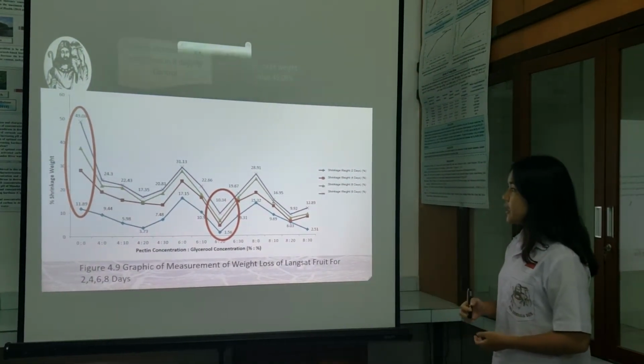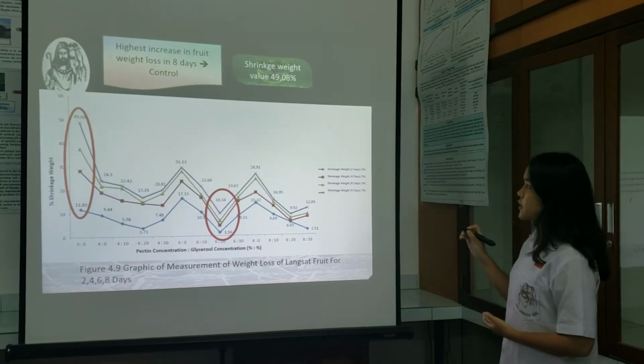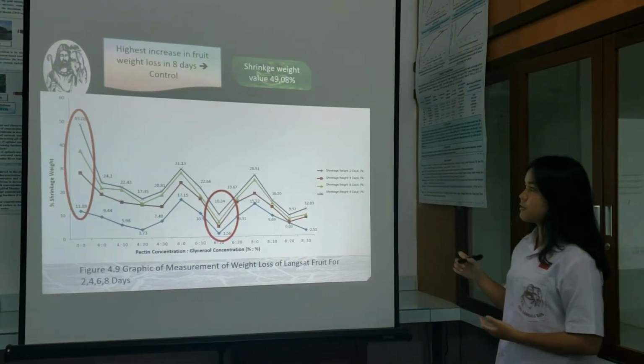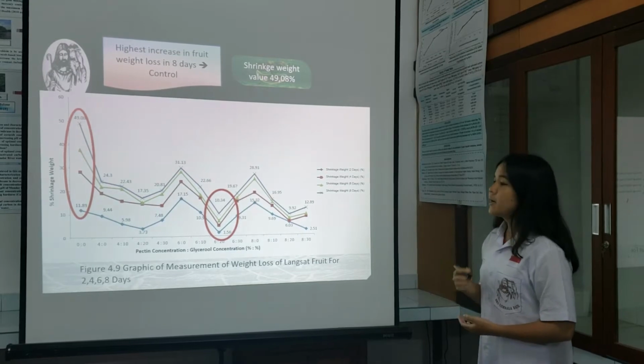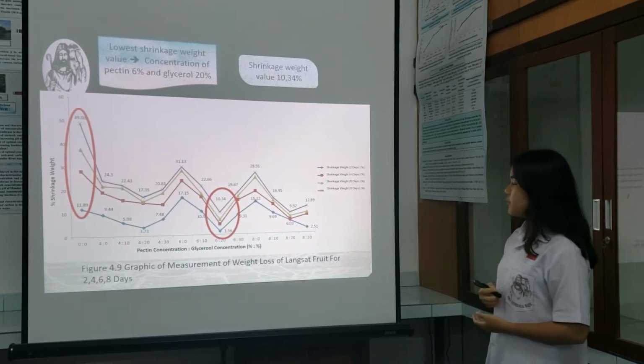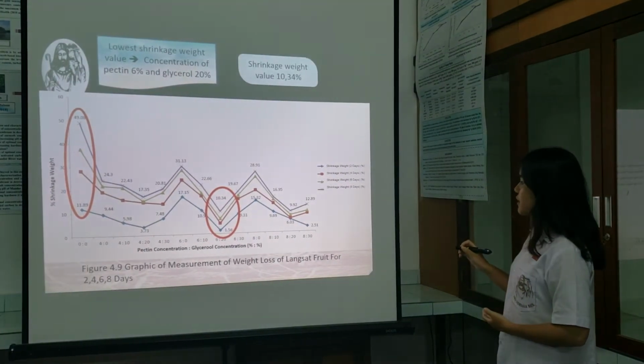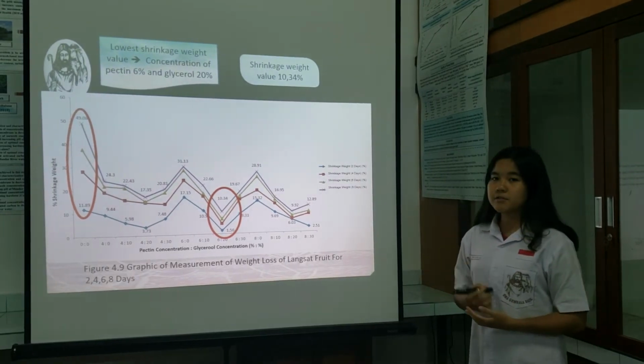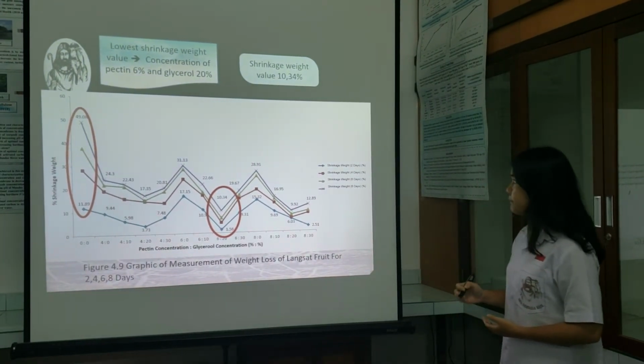In comparison, in the time of 8 days, the Langsat which is not coated with edible film experienced a shrinkage rate of 49%. Meanwhile, the Langsat which is coated with optimal edible film, which is 6% pectin, 20% glycerol, only experienced a shrinkage rate of 10.3%.